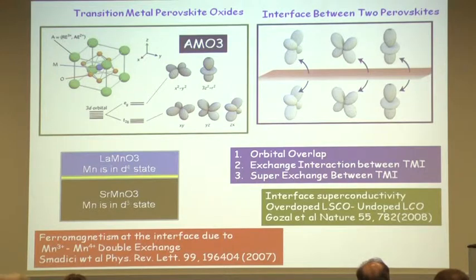For example, this is not a perovskite, but a similar family of compound. You take overdoped lanthanum strontium copper oxide with strontium doping about 45% or so, so it is no more a superconductor, it's a Fermi liquid. And if you make an interface between this and undoped lanthanum copper oxide, it turns out that the interface becomes superconducting with a TC as high as 45 to 50 K. Another purely interface-driven phenomena.